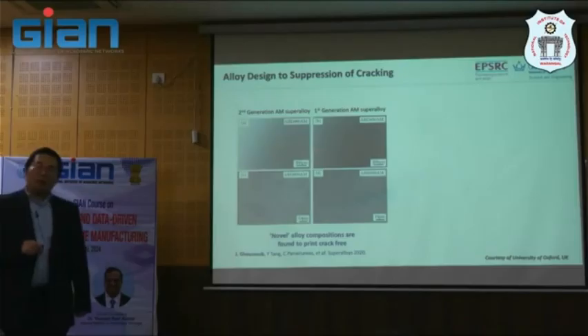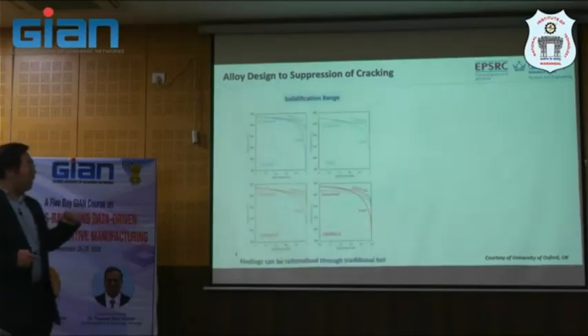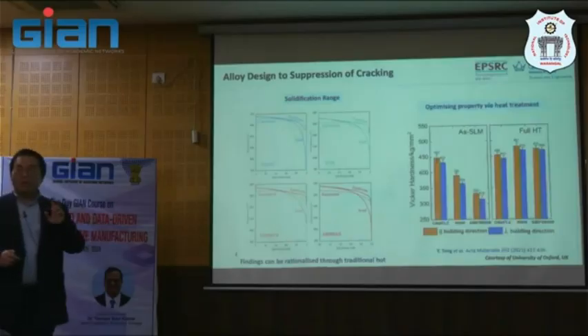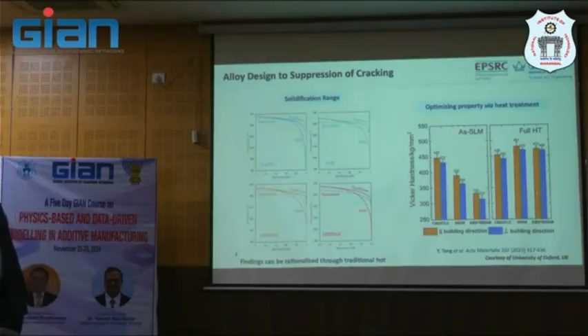But what actually happened when you are here? They expect to have about 25 to 35% gamma prime, but it's printed as solid solution. It's printed as solid solution. I can show you in the next lecture. It's proved by so many means of experiment. It's solid solution. But that's what I said to you. We print soft, and then we recover the strength later. This is what it does.